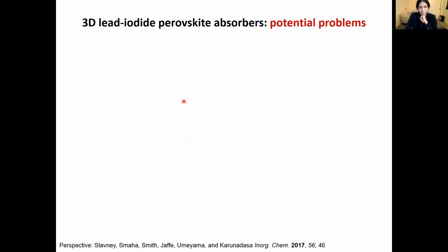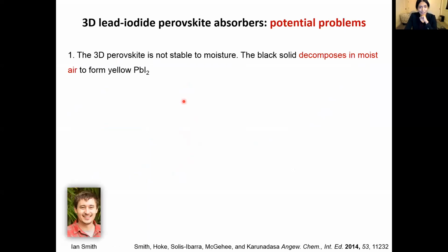So the first is that we noticed very quickly, along with anyone else who has worked with this material, that it's not stable to moisture. So the black solid, methylammonium lead iodide, will decompose under ambient conditions and form yellow lead iodide, probably faster in Colombo than in Palo Alto. And once you get yellow lead iodide, you basically don't have a solar absorber anymore.